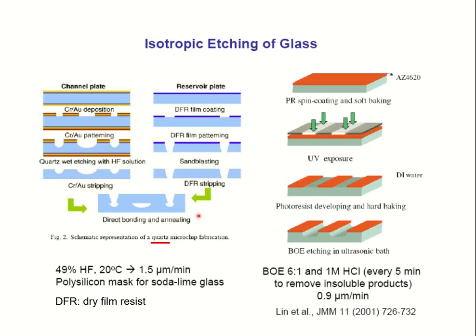Sometimes transparency is really important to observe what's going on inside. For example, if some liquid is passing through those channels and has some color, you can dye it actually. Then you can observe what's going on through the process, right? So it's easy to observe under a microscope or with the naked eye. For example, to make this fabrication, they use a chrome gold mask for the patterning in this case. And then they protect both sides with chrome and gold, and they are etched by the HF solution. And then the chrome and the gold were stripped.